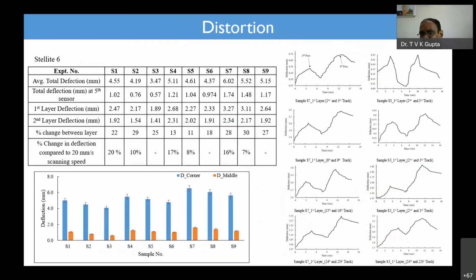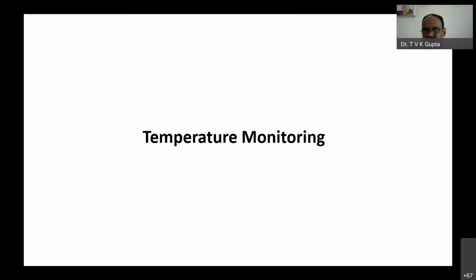Now, different parameters we studied, because each layer got almost 16 tracks, right? And up to 2 layers we have worked. The next set is that we went up to 12 layers, that's a different part. So we started with Stellite 6, I told you, 2 layers we have done, and we are understanding how the track temperature is being changed, how the layer temperature is also changed. Because temperature always leads to deformation, deformation leads to distortion.